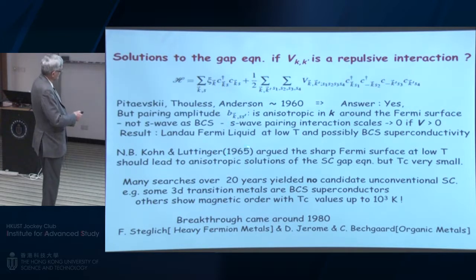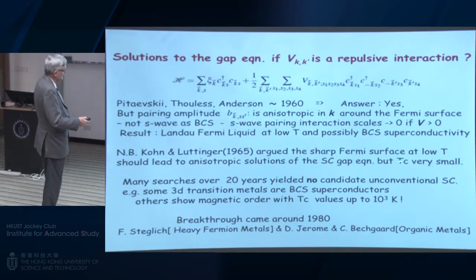But there were speculations by Kohn and Luttinger that there could be solutions to the gap equation caused by the singularities in Q space associated with the sharp Fermi surface at low temperature. This could lead to anisotropic solutions of the gap equation, but the Tc they predicted was very small. So this idea came in 1960, but for a long time, there were no candidate superconductors around.